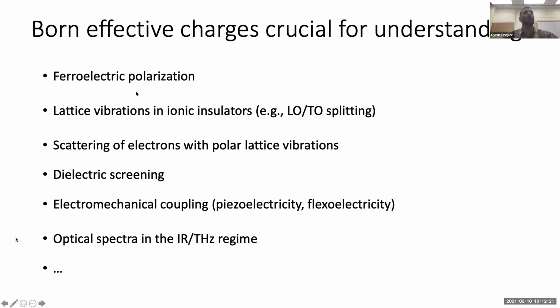Born effective charges. If we have lattice vibrations in ionic crystals, if we want to calculate phonons, we need Born effective charges for properties like the LO-TO splitting, the splitting between longitudinal optical and transverse optical modes. Also in transport, when we're interested in how electrons and holes scatter with polar vibrations in crystals, the Born effective charge is in there. Also dielectric screening, the lattice contribution to dielectric screening, lattice contribution to electromechanical coupling, piezoelectricity, flexoelectricity, they have terms with Born effective charges, optical spectra in the infrared and terahertz regime, et cetera, et cetera.